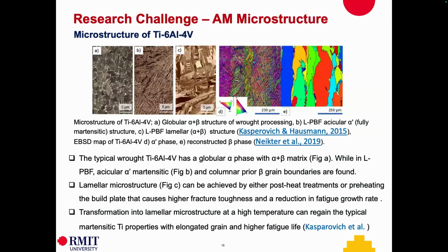Okay, now what is important from this slide is I would like to highlight the role of microstructures. And this is an example of 3 different metals, which I'll show. First thing we did with Ti6Al4V, the titanium alloys. And what we can see, the typical wrought metal has got globular alpha with alpha plus beta matrix, whereas in the LPBF, we can see martensitic and columnar prior beta grain boundaries. So that's typical of what we found from literature, this type of microstructures are produced.